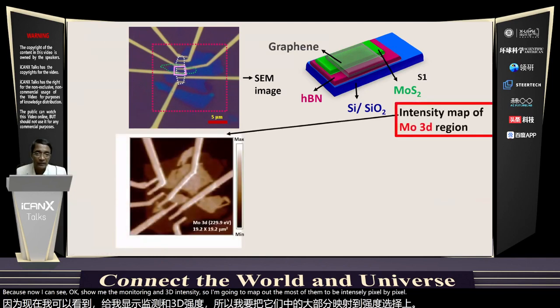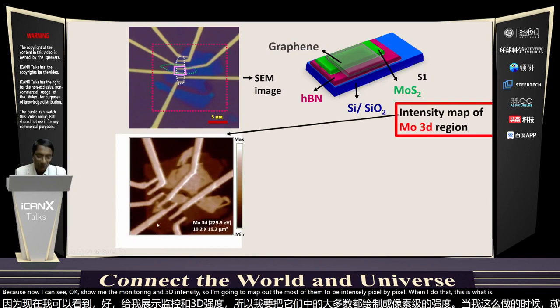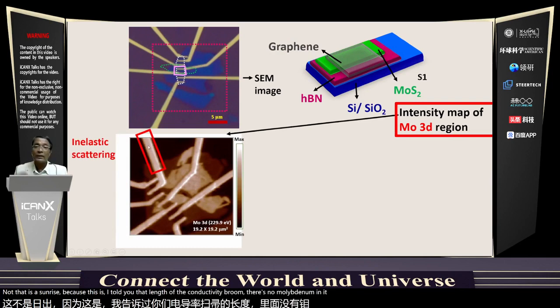But what I want to point out here is the power of the technique that I talked about, because now I can say, okay, show me the molybdenum 3d intensity. So I'm going to map out the molybdenum 3d intensity pixel by pixel. When I do that, this is what I see. Now, there is a surprise because this is, I told you, the legs of the conductivity probe. There's no molybdenum in it. It is coming because of inelastic scattering.